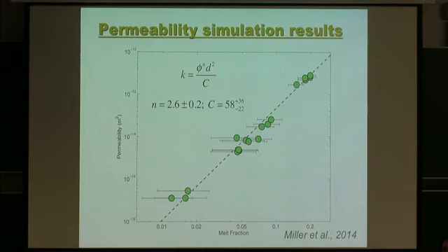So what we did was, if you assume this pixel is completely melt, then that's the lower end of olivine and the higher end of melt. And then if you assume this boundary pixel is completely solid, that is the lower end of the melt volume, all right? So that's why each one of them has the uncertainty.